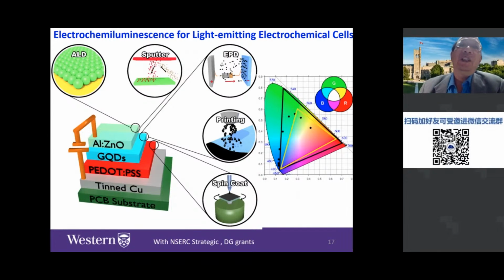Another application we are doing here at Western is called a light-emitting electrochemical cell, and we would like to use graphene quantum dots. We take tinned copper on the PCB, then use the PEDOT:PSS conducting polymer to flatten the surface, add the GQD, the graphene quantum dots, and then aluminum-doped zinc oxide. In this way, it's done.